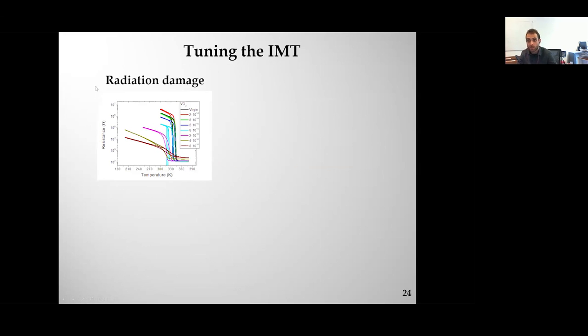Maybe the most promising one is using radiation damage. Radiation damage is very effective to control this insulator to metal transition. Here you have resistance versus temperature in VO2. You can see the insulator to metal transition for different doses, in ions per square centimeter. As we increase the irradiation with oxygen ions, we can not only reduce the amplitude of the transition, but also move the transition temperature to lower temperatures. So one possibility would be to use a focused ion beam to locally irradiate your film, with a resolution better than a micron. So you can write where you want to have a synapse and where you want to have a neuron.